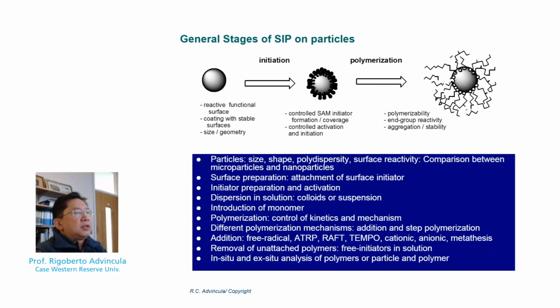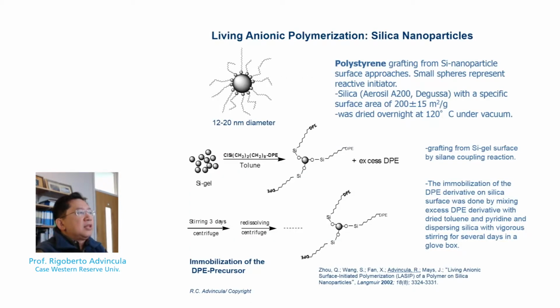But first, just to emphasize that what we can do on a flat surface, we can do on a particle interface as well. Particle polymerization simply means that the grafting is done, again, by tethering the initiator on the particle with a number of strategies outlined earlier, chemisorption or even physisorption, and then followed by the polymerization on the particle. So what happens is we achieve a core shell geometry where the core is the particle substrate and the shell is the grafted polymer brush. Here's an example of how we have achieved anionic polymerization of polystyrene on a silica nanoparticle.